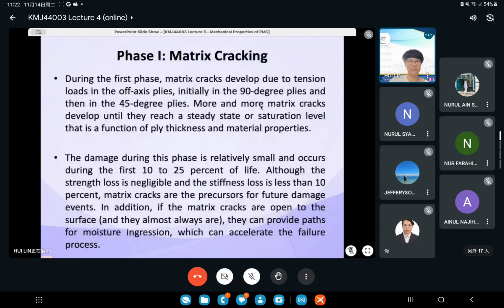Well, let's talk about this. For the first one, the first phase is the matrix will crack. This is very easy to understand and very easy for you to explain. And then although the strength is lost, in addition the matrix crack opens to the surface, and can provide a path for moisture ingression. So when the matrix cracks, it opens the path for the moisture to enter the matrix, the sunlight. If we place things in an outdoor area, even indoors we also have light. The light also has UV, and we have fans, the wind, and then we have humidity, other water molecules surrounding, so they will enter this polymer crack zone, and it will actually accelerate the crack, no?